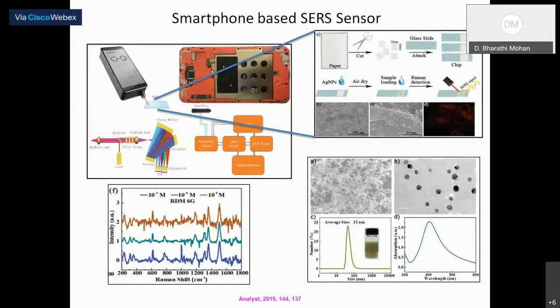Recently, scientists have developed a smartphone based SERS sensor, and in this device the SERS substrate has been fabricated on a paper based substrate by drop casting silver nanoparticles. 3 different concentrations of rhodamine 6G have been prepared, with molarity ranging from 10⁻³ to 10⁻⁵, and this smartphone based SERS sensor is able to achieve a limit of detection up to the level of 10⁻⁵ molarity.